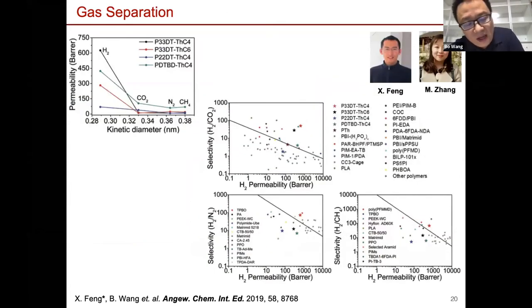And also, when you have smaller pores, in this case CMP and some COF membranes, you can separate hydrogen from carbon dioxide, nitrogen, and methane. In this case, you can effectively separate hydrogen. I would like to point out, separating those gases actually is not that hard, especially when we're talking about the pure MOF membrane. But when you have a self-standing pure COF membrane or pure flexible membrane, that will be more interesting because you can always make a final device out of it. In this case, we make the fiber, using such a self-standing membrane to separate hydrogen. So it will be easy to scale up the whole process.